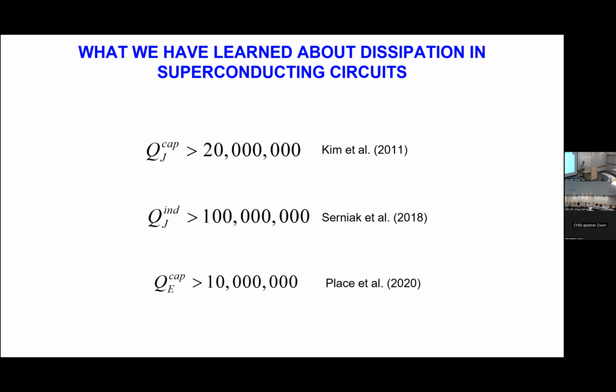Now, when you say quasi-particle, you're referring to the broken Cooper pairs? Yes. Is it clear the origin of this in BCS? We think that the origin of these broken Cooper pairs is twofold. There's parasitic radiation that enters in your box, far infrared radiation, radiation above the gap. So you have to be very careful in isolating your circuit from this parasitic radiation. But there are also phonons in your substrate that can break Cooper pairs. And these phonons, we believe, are produced by radioactivity. So you have particles traversing your substrate, and that creates shock waves, and these shock waves actually break Cooper pairs.